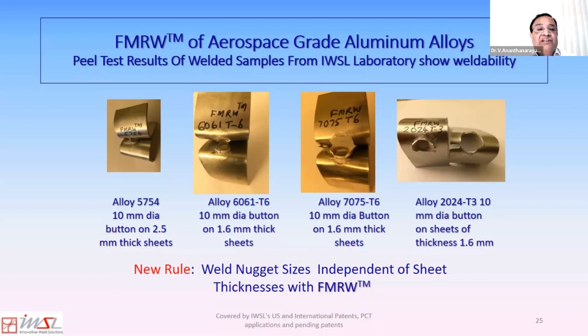And the thickness of the sheets welded is not the same. The 5000 series alloy has 2.5 millimeter thick sheets welded, and the 6061 alloy has 1.6 millimeter thick sheets welded, and they both have the same button diameter. So the focused melt resistance welding method allows you to select the weld size irrespective of the sheet metal thickness. And that way you can also select the weld strength of a particular spot weld as well.